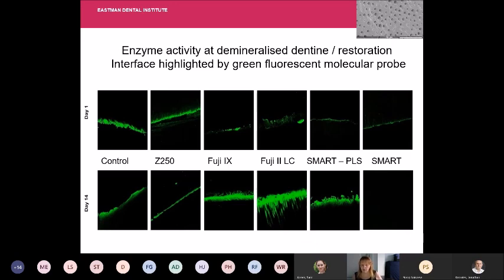And what we find with all these different commercial materials, Z250 is a composite, Fuji IX is a GIC, Fuji II LC a resin modified GIC, and this is our smart composite with the polylysine removed, and smart composite. All of the commercial materials have extensive green fluorescence showing that the enzymes are active at the restoration interface. Smart composite, there is some activity to start with, but at 14 days it's nothing. So it's really managing to stop this enzyme action that would cause degradation of the collagen.